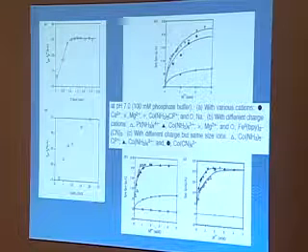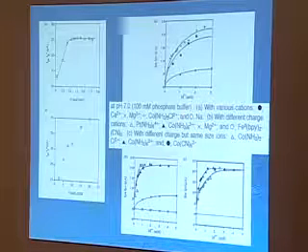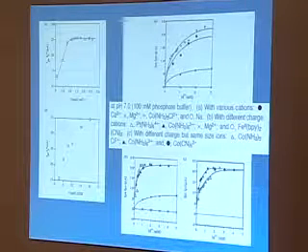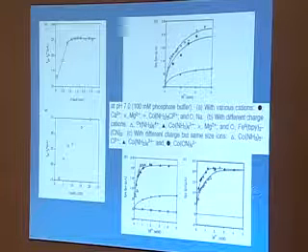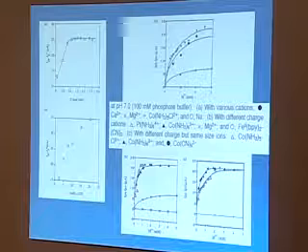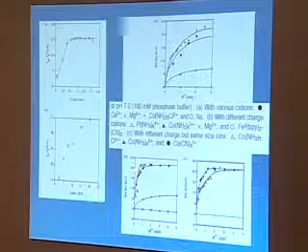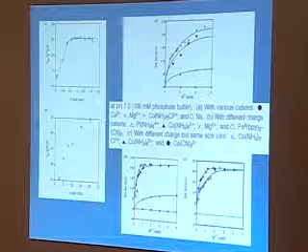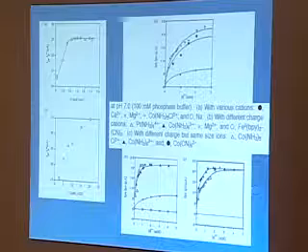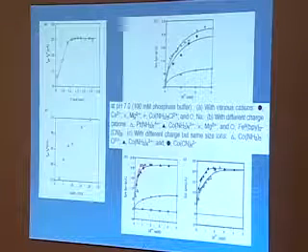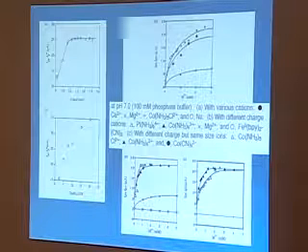And then we said, well, if 2+ is good, maybe 3+ or 4+ is better. So we started looking at all these complexes with very high charges. The highest charge we have here is a platinum hexaammine 4+ species. That's down here, and it's our best one. It has some solubility issues. We couldn't go as high in concentration, but that's the best one. Although this cobalt hexaammine 3+ species is very similar, the platinum beats it by a little bit. So the more charge, the better. And then we said, well, again, is it really the charge?